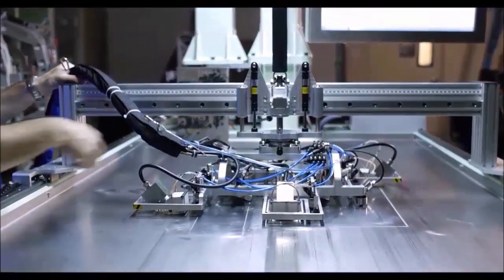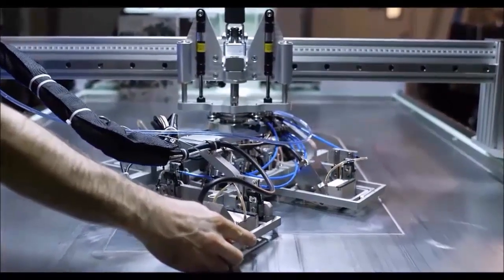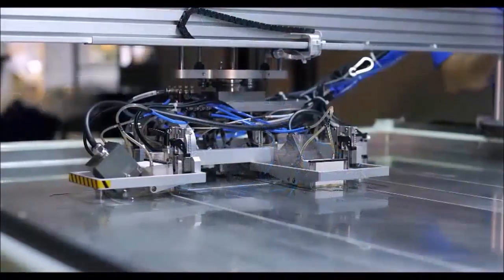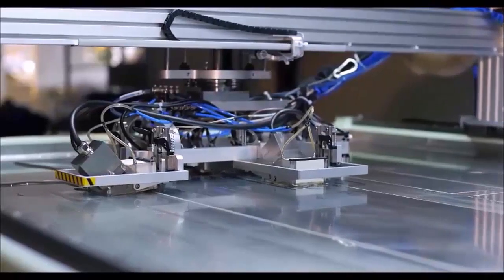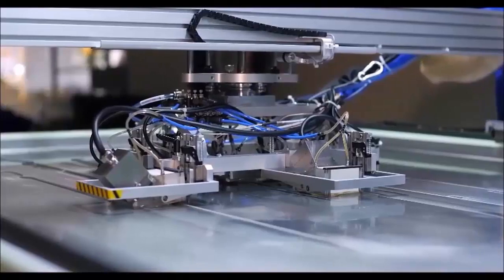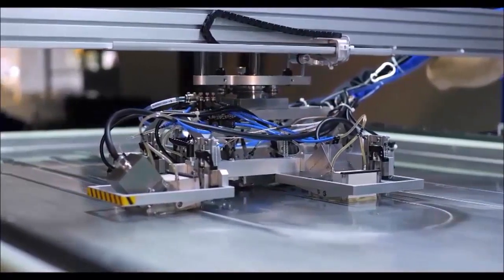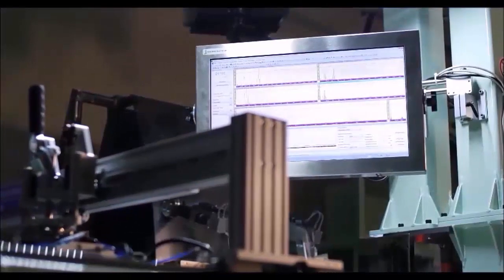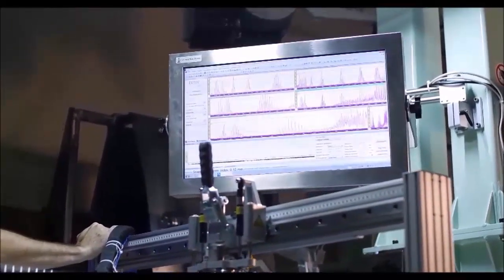The manual XY scanning system allows for a manual but well-controlled and encoded movement of the complete probe pan over the calibration block surface. If required for special inspection techniques, the probe pan can also be oriented in different directions to optimize the insonification of the calibration reflectors. Coupling liquid supply and recuperation is automatically controlled. The probe pan is moved manually over the calibration block surface. A semi-automated verification procedure using the calibration tool embedded in the UltraVision Classic software allows for fast calibration checks with automated reporting, including date and time stamps.